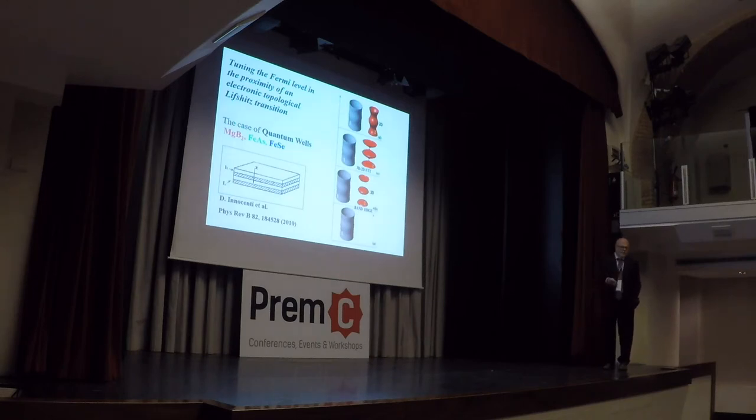And many Russian theorists moved to different countries, and so now became very popular. What we discovered was that actually all the superconductors, when this is maximum, you are at the Lifshitz transition. You have many different kinds of Lifshitz transition because in topological states, for example, this is one where you have a two-dimensional Fermi surface, and then you have a new Fermi surface appearing that is circular, then you have like a Dirac point, and then you have an open circular. And the maximum TC happens always in this case.